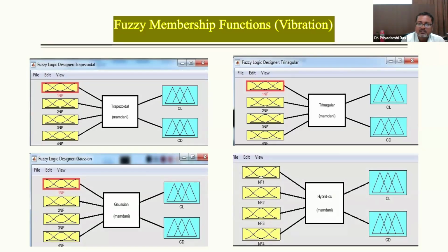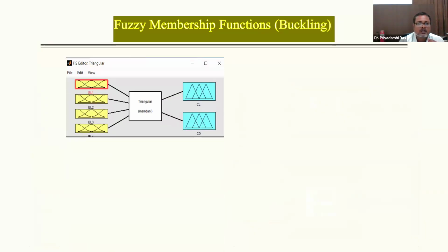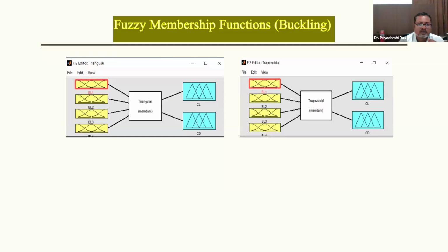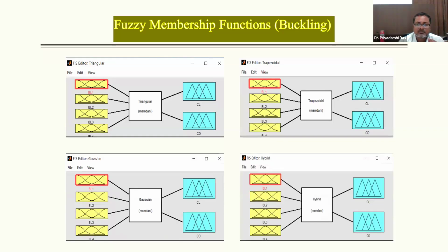Through that FIS simulation that we discussed earlier, after defuzzification, it gives the result as crack location and crack depth. Whatever crack location we got for triangular, it will be more crisp for trapezoidal, then Gaussian. Then after the hybridization, we got the most crisp value, or the value closest to the numerical or experimental values. In the same way, the buckling analysis was also done, with the four modes of buckling, that is buckling load 1, 2, 3, and 4, and through that Mamdani analysis, triangular, trapezoidal, Gaussian, and hybrid, we got the values.